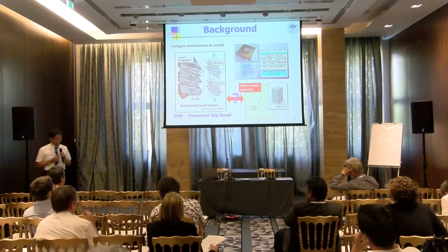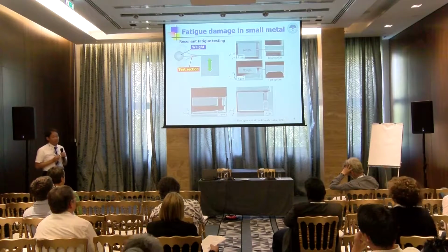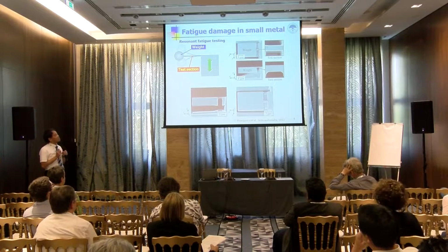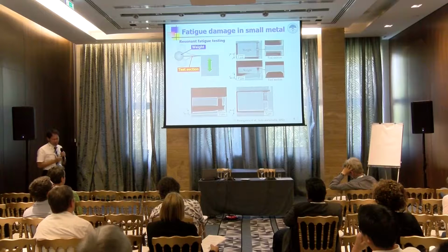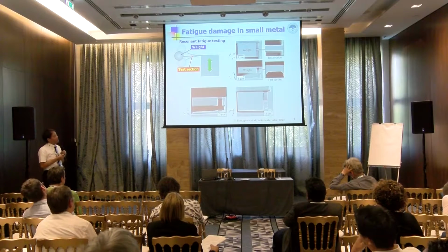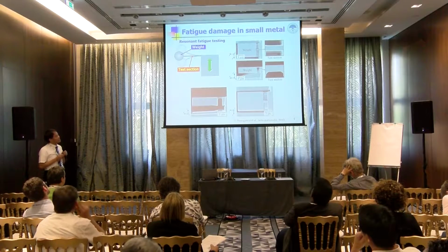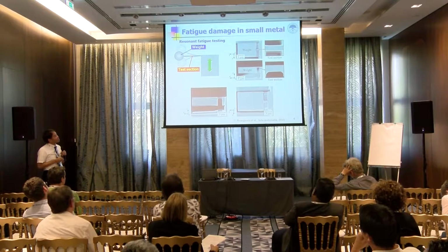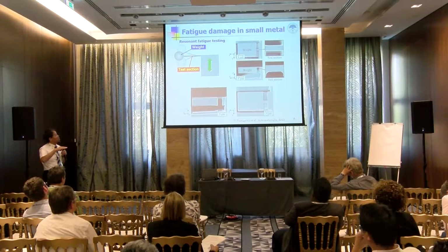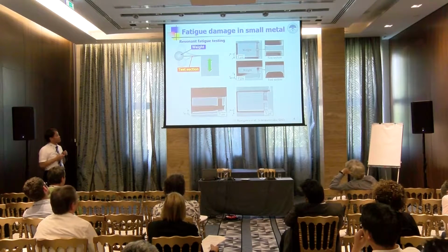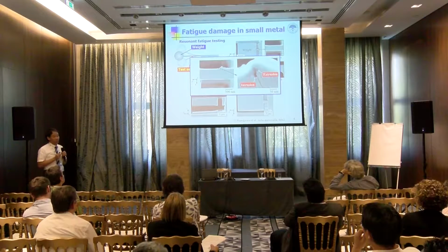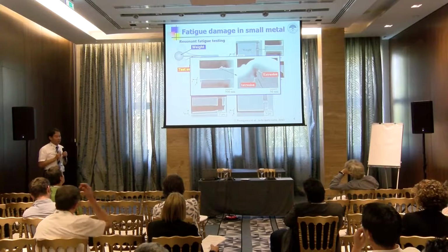So in order to examine that, in our previous study, we conducted cyclic loading experiment for the nanoscale single crystal gold specimen. The test section is located here, and this method utilizes resonant vibration. And in this experiment, we found the generation of intrusion and extrusion.